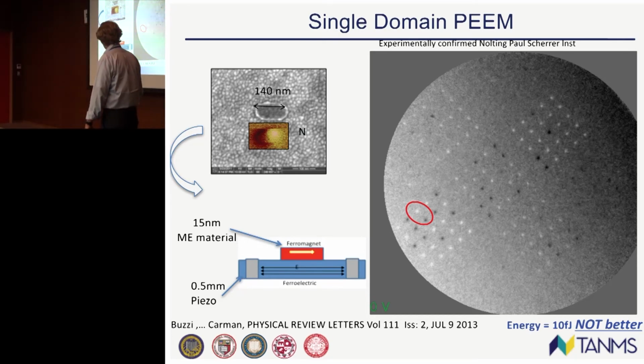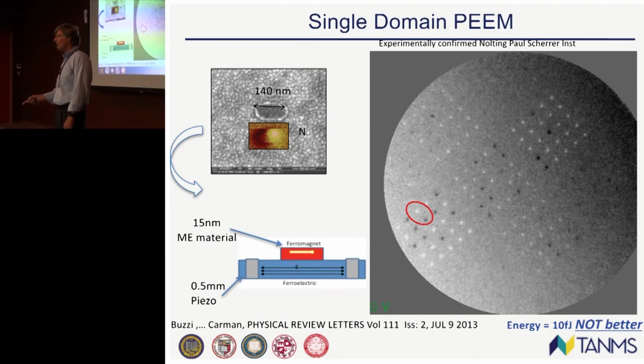Now if you'll notice here in the bottom left, you'll see a voltage counter going up. And what you'll see is if you look at this circle region here, let's get back to 0. White and black, and as you increase the voltage, all of a sudden they pop to gray. So now this is probably the first demonstration of electrical control of spin states using strain-mediated effect in a single domain structure.